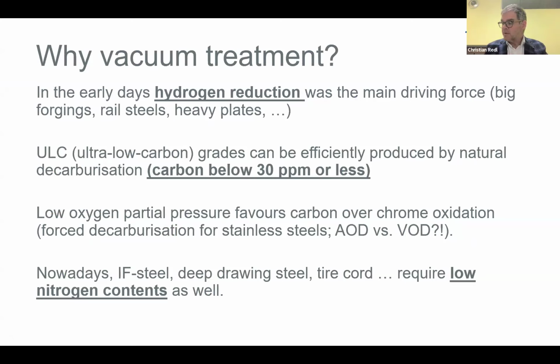Of course, this has also been addressed by Ahmed and Professor Iman in their previous lectures: why we are doing vacuum treatment. In the very early days, it was mainly done to reduce the hydrogen content in the castings, which is today still done for forgings, rail steels or heavy plates. This was the main driving force in the early days. Then there was the invention of ultra low carbon steel grades, which can be efficiently produced by decarburization under vacuum to carbon contents below 30 ppm or less.